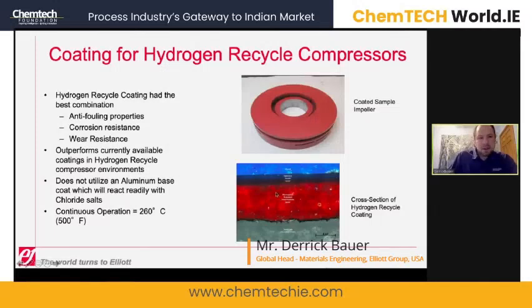So the cross-section of the coating that is useful for hydrogen recycle service is shown here, whereas basically a permeation resistant intermediate layer along with the non-stick top layer is applied. This coating is utilized up to 260 degrees Celsius, which is normally well beyond the maximum temperature that hydrogen recycle coatings would see during service. And again, this was a coating specifically for ammonium chloride deposits, which again, the industry standard coatings have not really looked at that application.